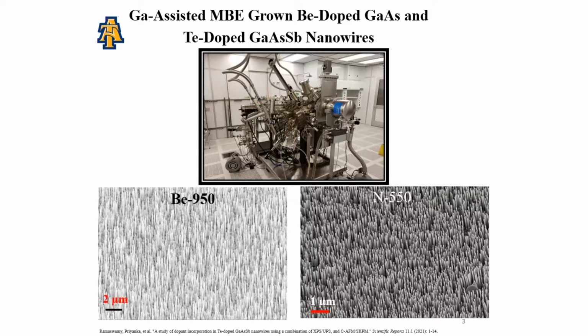The intrinsic, beryllium-doped and tellurium-doped nanowires were grown in an EPI 930 solid source MBE system with valved arsenic and antimony as the group V constituent cracker sources. On the left side, an SEM image of the ensemble beryllium-doped gallium arsenide nanowires grown at beryllium cell temperature of 950 degrees Celsius is shown, whereas on the right side, an SEM image of tellurium-doped gallium arsenide antimonide nanowires grown at gallium telluride cell temperature of 550 degrees Celsius is shown.